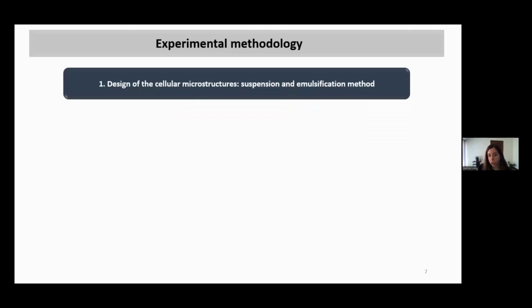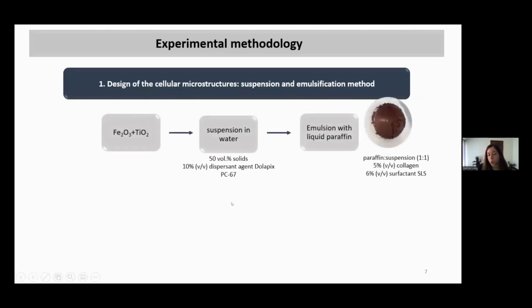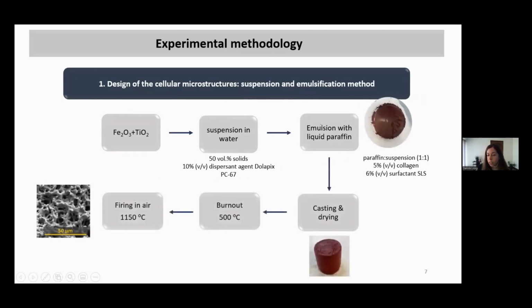The design of the cellular microstructures was chosen by the emulsification method. So basically, we mix hematite with titanium dioxide in a water suspension with 50% of solids and with a dispersant agent, and we added liquid paraffin. Liquid paraffin is necessary to create these porous structures. So we have a burnout at 500 degrees. Of course, this releases CO2, but this is just at lab scale. So in future, this is not going to be used. Here, we just want to study the mechanism of reduction and how it works. For pilot scale, for sure, it has to be done by suspension mode.